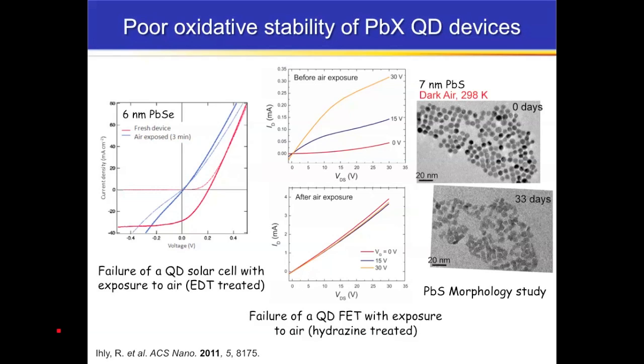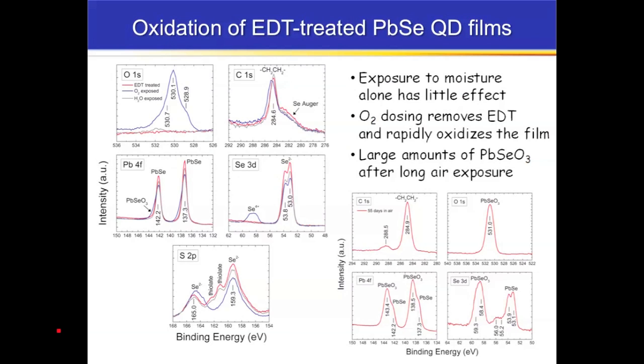And then we can use ex situ TEM to look physically and see what happens to dots after long air exposures. And you can see basically that they look like they're corroded, essentially. And this is because of oxidation as well as diffusion of the material. And so we've studied the details especially of the oxidation process on EDT-treated lead selenide dots. We can use in situ gas dosing and XPS, X-ray photoelectron spectroscopy. And what we're able to find is basically the initial oxidation is due to oxygen, not to water. And so we can see a large oxygen peak that shows up. We oxidize the selenium, and we also lose the ethane dithiol molecules. They volatilize off the surface. And after long periods of air exposure, we build up a shell of lead selenite on the outside of all of the lead selenide cores. And this is going to interfere with charge transport.